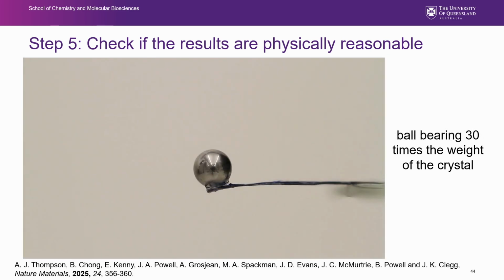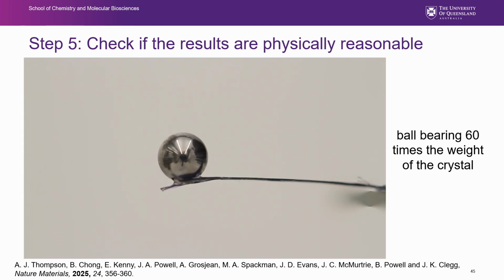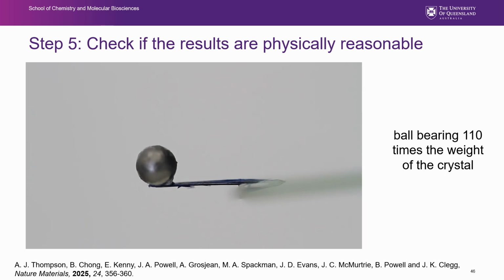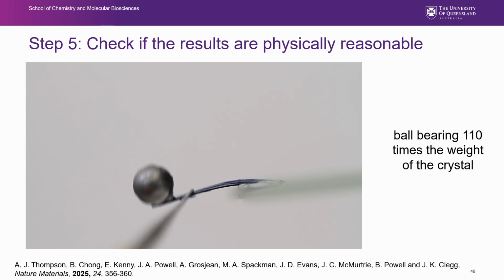And why is that important? Well, really it's important because that shows that we're doing work against gravity. So we're really springing back more energy than we put in. So we go from 12 times the weight up to 30. Still elastically flexible. We can go up to 60 times the weight of the crystal. Probably getting to the edge, we're getting some deformation there, pushed it down too hard. But we can keep going on, we can go to 110 times the weight of the crystal. Again, thinking that this is getting close to our limit of 70 joules per mole, I guess, in some ways. Still elastically flexible if we don't push it in too far.